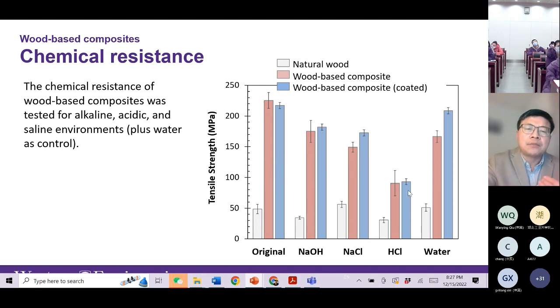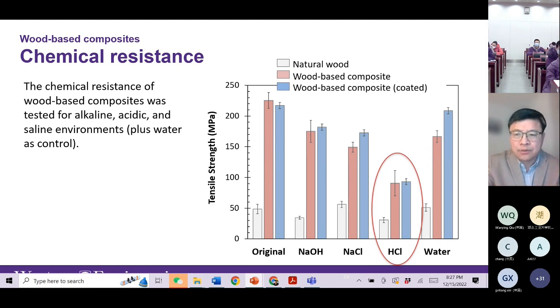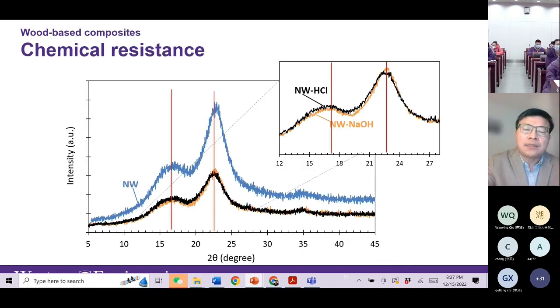So this material may not be suitable for acidic conditions. For some reason, we did some investigation on that. Why does the acid condition make this material lose intensity, lose strength? So we did some XRD analysis.